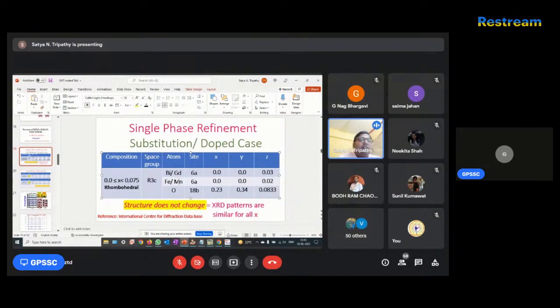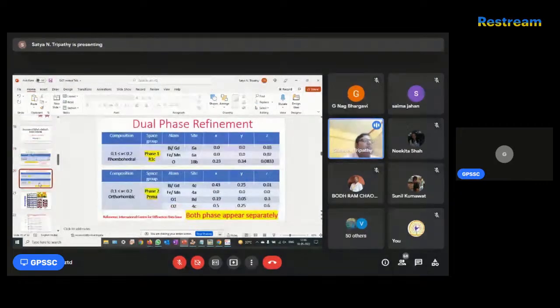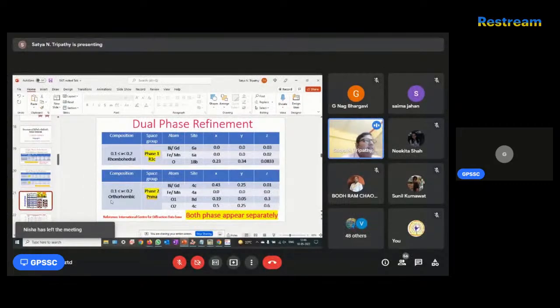So what we are actually seeing is an ABO3 type structure that may be bismuth ferrite, gadolinium manganite, bismuth manganite, or gadolinium ferrite. All these kinds of structures are possible, so we are going to give these kinds of atomic positions. Here the structure doesn't change because the XRD patterns are similar. These atomic positions have been collected from the ICDD database, so you can take them if you are doing work with bismuth ferrite.